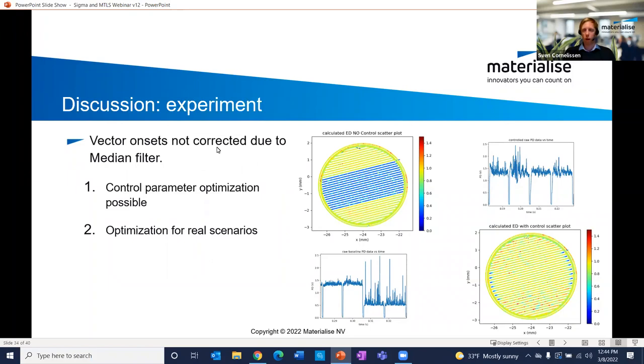Some remarks which lead to that remark about the increased porosity in the nominal zone. I already mentioned that the onsets of the vectors seem like they are not correctly controlled out yet. And I think in these 2D plots, which is actually a plot of the energy density as it is calculated on the MCP, you can see even a bit better that those onsets of the vectors, the starts of the vectors, are still scanned with a lower energy density, right?